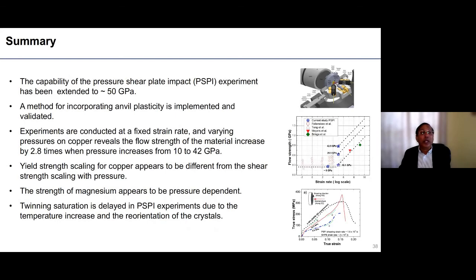So let me conclude. I hope I have convinced you that we can extend this pressure shear plate impact experiment to higher pressures. In this case, we have extended it up to 50 GPa, and obviously we can take this to higher pressures if we can find good anvil materials as well as other techniques to impact at higher velocity. One of our main contributions has been to incorporate the anvil plasticity, and we have shown that in copper the flow strength increases about 2.8 times, or about 3 times, when the pressure goes from about 10 to 40 GPa.